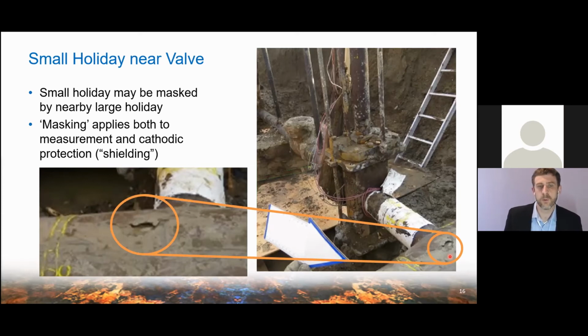Now we didn't see the coating defect on the T, at least I couldn't point it out in the data. So what's going on? Well, we can have what's called shielding when we normally talk about cathodic protection. Effectively, this valve is partially shielding this, and that represents itself in our DCVG data as a term I'll call masking. So you can't see this little tiny coating defect because you've got that big coating defect. Now, what's the significance of that? Well, I'm fully protected, so I guess I'm not really concerned. And in fact, when you've got a valve that's fully protected, you got good confidence. You move a little bit away, you're going to be fully protected on the coating defect as well. However, if you're not fully protected, then that introduces uncertainty.